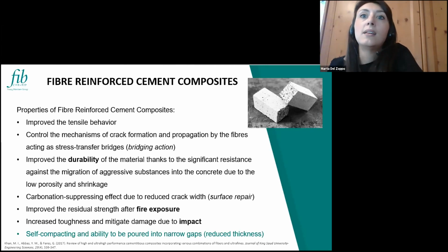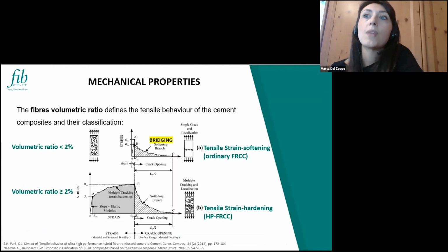And finally, they have an improved residual capacity under high temperatures, so for fire exposure, and also a high toughness that can ensure good resistance against impact loads. And last but not least, these materials are self-compacting in the fresh state, and so they can be poured in very narrow gaps, allowing them to be applied on structures in very, very thin layers. And this is a very good and important characteristic when we deal with strengthening applications.